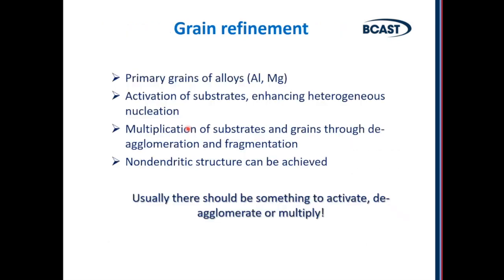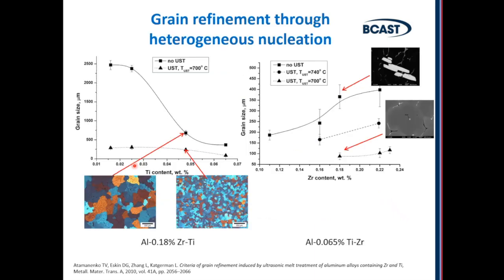So when we talk about grain refinement, so this was a refinement of primary intermetallics or primary phases. If we talk about grain refinement, we talk about primary grains of base materials, so aluminum or magnesium. And here we want to activate substrates, multiply nucleation points, and you can actually achieve non-dendritic structure if you have excess of solidification sites. What we suggested a few years ago, and we use it, is you can combine these two.